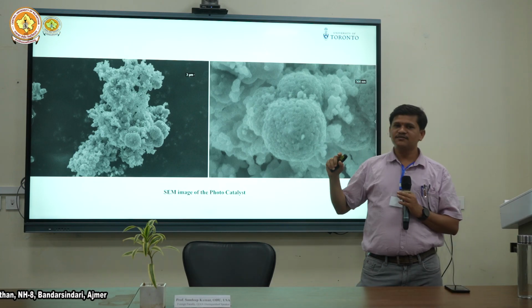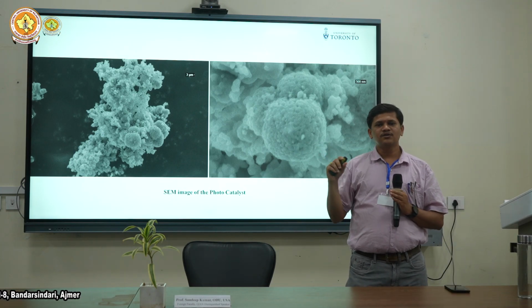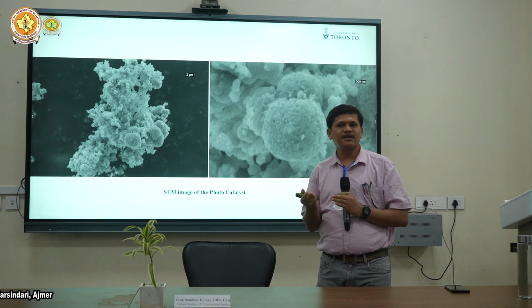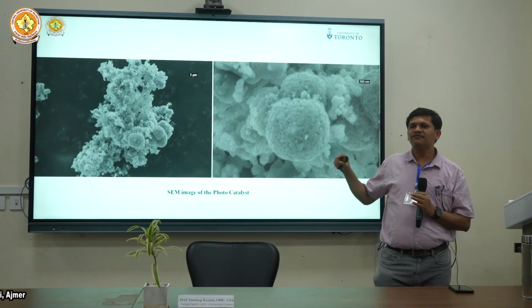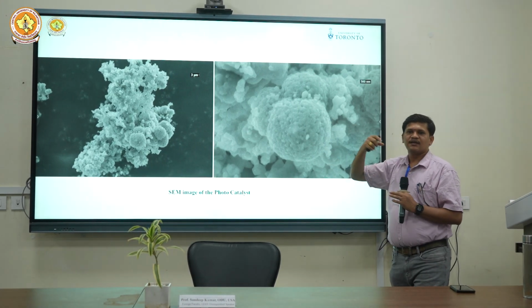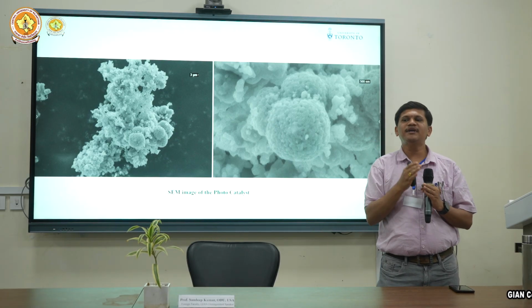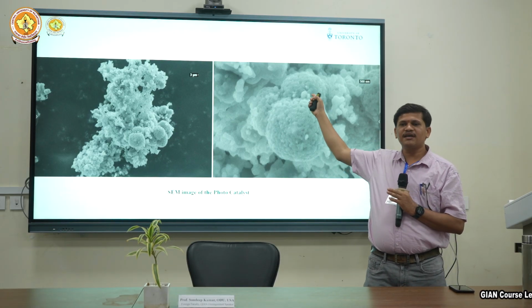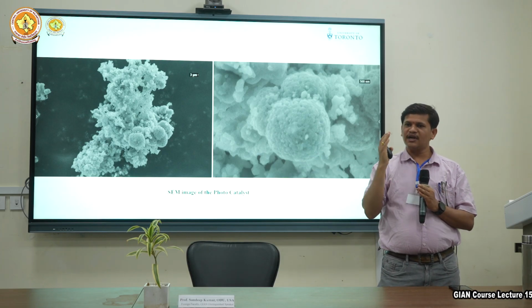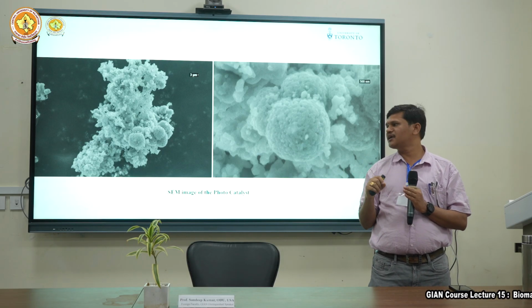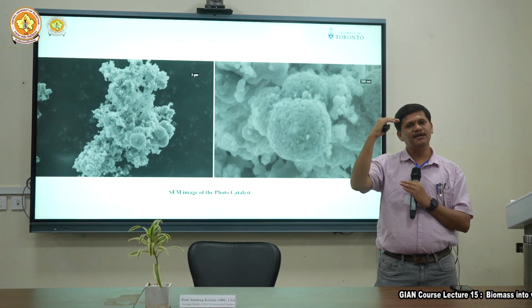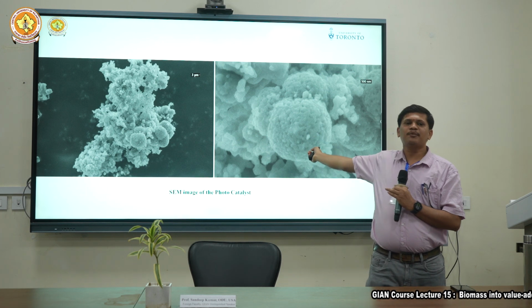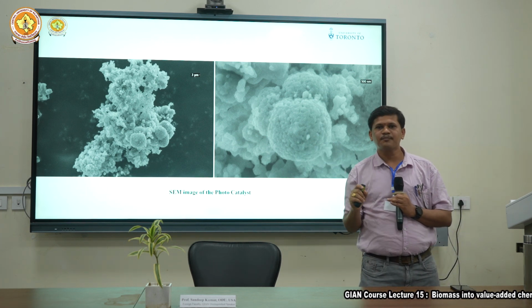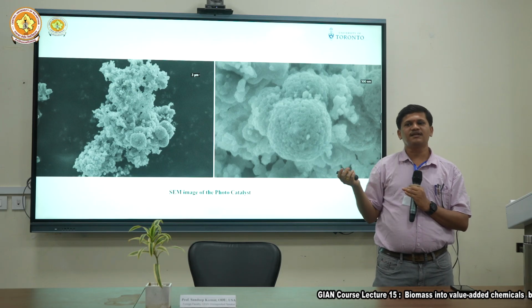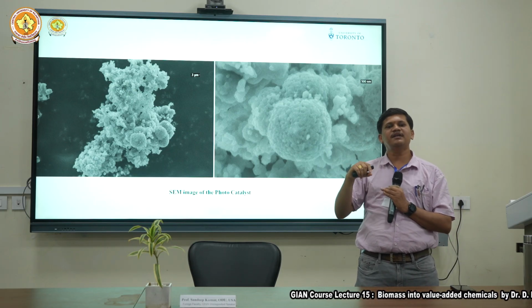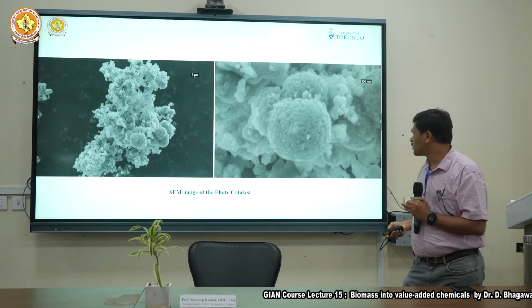And this is one of the catalysts which was prepared from zinc oxide. The same conventional solvent methodology has been utilized, but the beauty of this catalyst is its porous nature, where the lignin has been trapped and degraded in controlled conditions. As I mentioned earlier, it degrades the controlled beta-O4 linkages and converts into a single component with the highest rate of conversion. As I showed in the previous results, the percentage of vanillin was only 30%. But in this case, we have more than that, nearly 70 to 75% vanillin produced from the lignin compound.